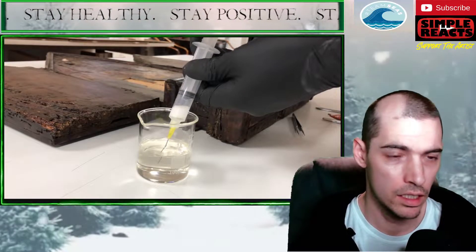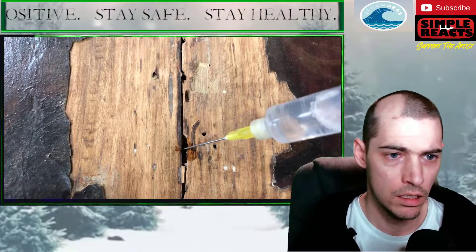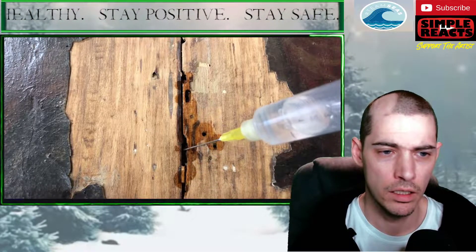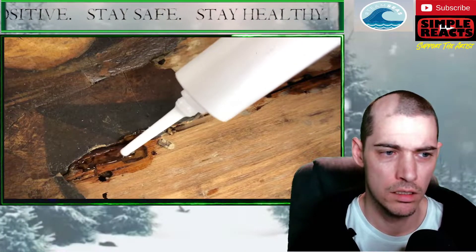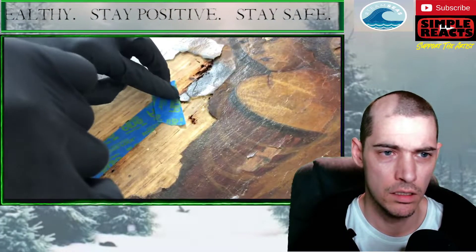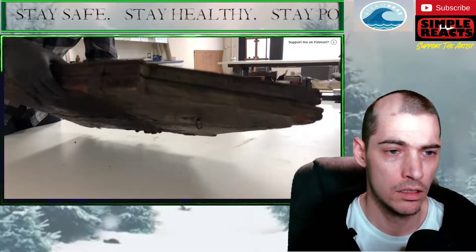In this case, the main reason for the separation of the paint from the panel was not only due to the movement of the wood, but poor preparation of the panel itself, as the paint layer separated at the gesso. So I'll remove all of the old gesso, all of the old rabbit skin glue, and any other materials I find on the panel to reveal the raw wood so that I can stabilize it and prepare a new layer for the paint. Wow. Okay.